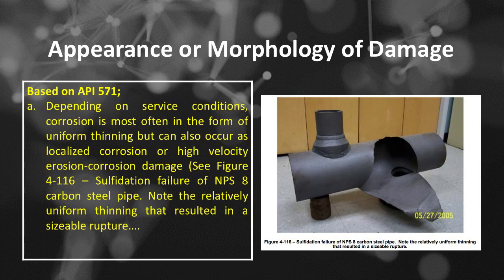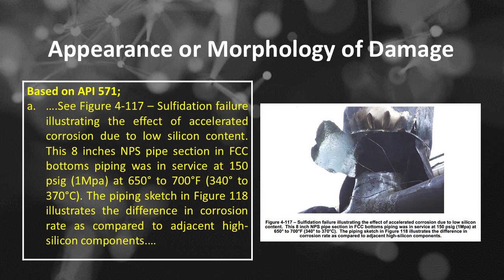Appearance or morphology of sulfidation damage mechanisms, based on API 571, number A: depending on service conditions, corrosion is most often in the form of uniform thinning but can also occur as localized corrosion or high-velocity erosion. Corrosion damage, see Figure 4-116, sulfidation failure of NPS-8 carbon steel pipe. Note the relatively uniform thinning that resulted in a sizable rupture. See Figure 4-117, sulfidation failure illustrating the effect of accelerated corrosion due to low silicon content.